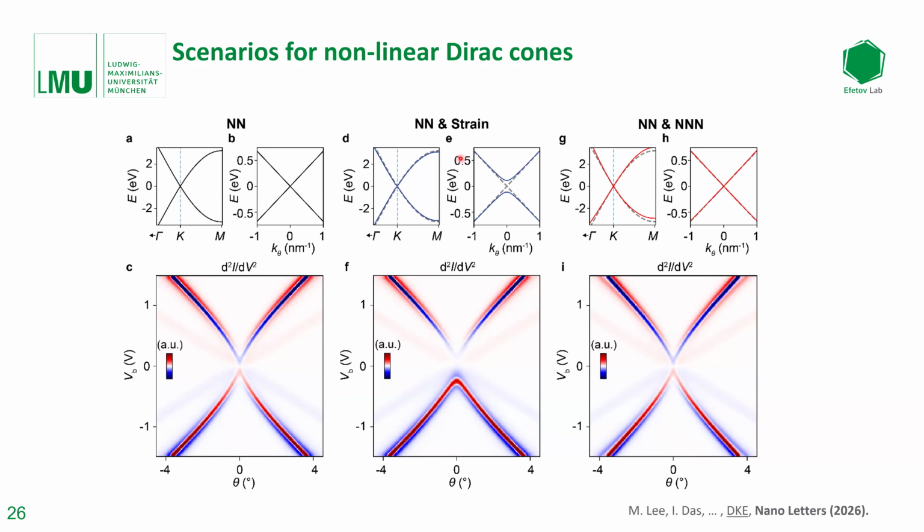The second scenario that we considered was strain, and we considered different cases like uniaxial strain, biaxial strain, and so on. The strain usually would give rise to some sort of gap-like looking feature, because the Fermi surfaces would not overlap perfectly with one another, and for certain momenta would bypass each other close to small twist angles.